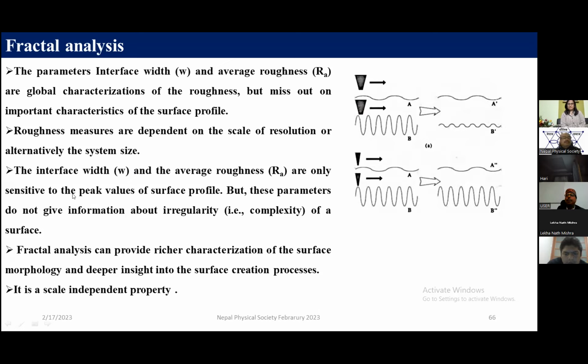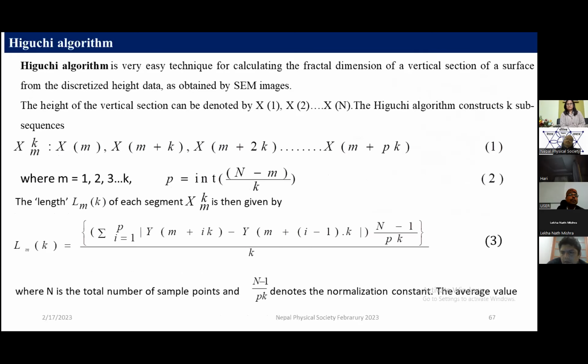Since my samples are thin films, if you calculate the interface width and average roughness, it is sensitive to the peak value of the thin film, but it does not give an idea about the irregularity or complexity of the surface. Fractal analysis can provide a richer characterization of the surface morphology, and it is a scale independent property. That is very important. There are many methods to analyze the surface. Here we are using the Higuchi algorithm.